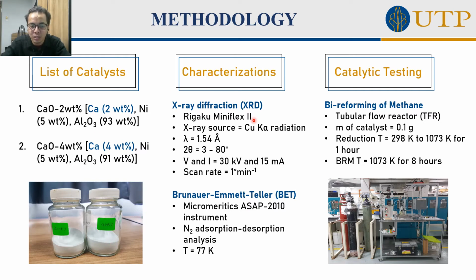For the characterization, the first one is X-ray diffraction, XRD, and the equipment is Rigaku MiniFlex 2. The X-ray source is copper K-alpha radiation, wavelength 1.54, range of diffraction 2 theta 3 to 80 degrees, voltage and current 30 kilovolt and 15 milliampere, and the scan rate is 1 degree per minute. The second one is BET, and the instrument that we have utilized is Micromeritics ASAP 2010. The analysis for BET is nitrogen adsorption desorption, and the temperature is acquired at 77 Kelvin.